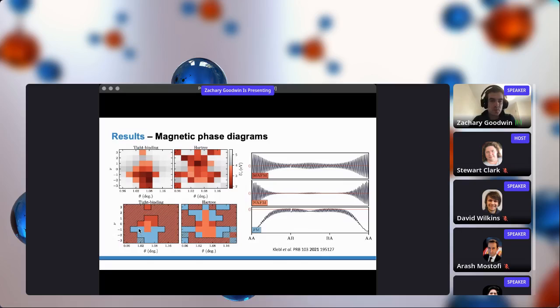So blue corresponds to ferromagnetic order, and this essentially occurs where the bands are the flattest. So in the tight binding case, this occurs right at the magic angle for hole-doped systems. Whereas for the Hartree interactions, it occurs over a much wider range of twist angles and doping levels. And in red and orange, we're showing different types of antiferromagnetic order that we can observe.